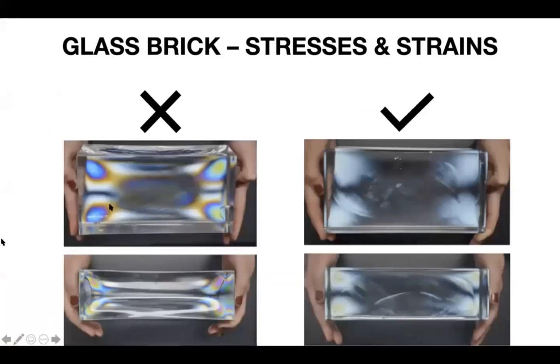So bricks on the left here, you can see there are some residual stresses which are distorting the light, and you can see they're creating these stress concentrations in the brick, which are very visible when you conduct this test, compared with the brick on the right, which has no visible strain concentration. So basically what they're doing at this point is using light to check for stresses and strains in the brick. If they're seeing stresses and strains, those bricks will be discarded, and those without stresses and strains are employed on the project.